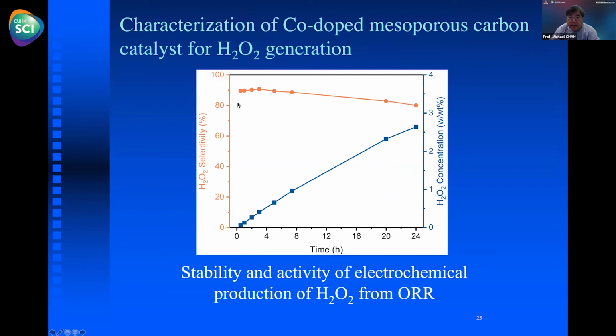The nice thing is the H2O2 selectivity. Here you can see it's primarily making H2O2, and then over time you'll notice that the H2O2 concentration increases in weight percent in solution as the catalyst is working. So this allows you to do continuous production of H2O2 using this oxygen reduction reaction.